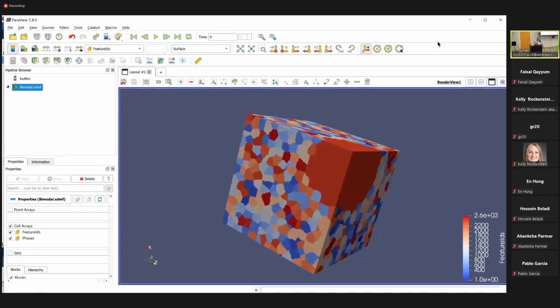So there are a couple of interesting things to note about this. One is that when you start trying to do something like this, with really big things fitting into the box, the best place it's going to almost always find to put them is in a corner or on a surface. So a couple of things to recommend there. Either make your box huge if you want to make sure you get a full grain volume from something that's big, or put on periodic boundary conditions.